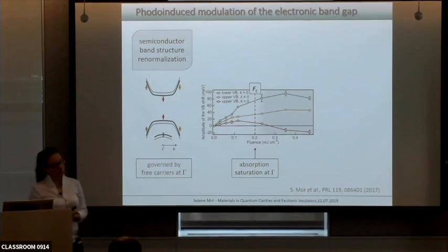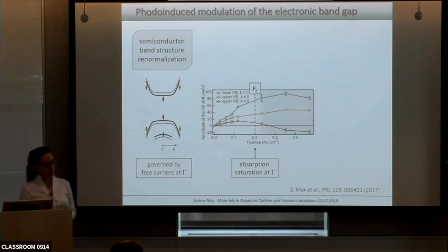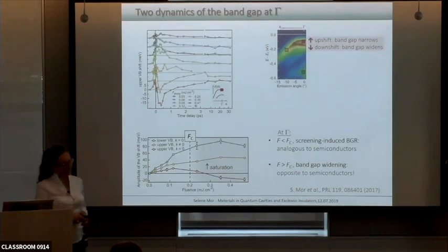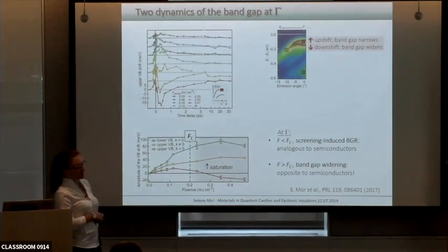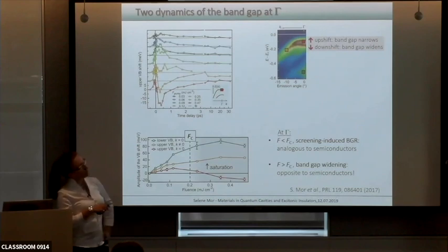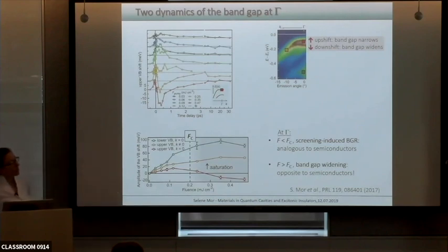Because your temporal resolution is 100 femtoseconds, I guess. So there's always a rise time involved. I totally believe the data, it's crystal clear, but the interpretation of the band gap renormalization doesn't convince me, because in the real data there's a rise time of the response, which is 500 femtoseconds or so, or 100 at least. So we should find a good way to set time zero for all of us, not just you or me.